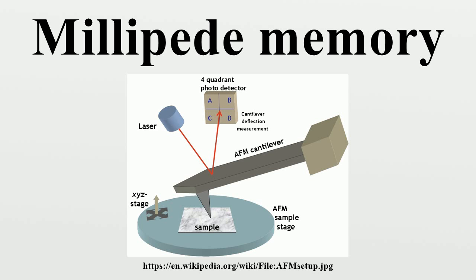Indentations have been made at 3 nanometers lateral resolution. By heating the probe immediately next to an indentation, the polymer will re-melt and fill in the indentation, erasing it. After writing, the probe tip can be used to read the indentations. If each indentation is treated as one bit, then a storage density of 0.9 terabits per square inch could theoretically be achieved.